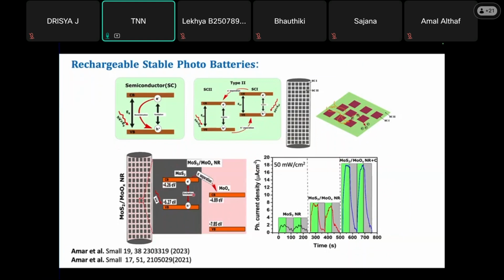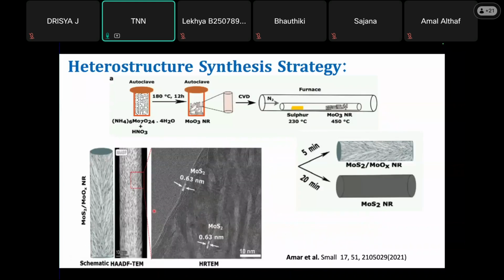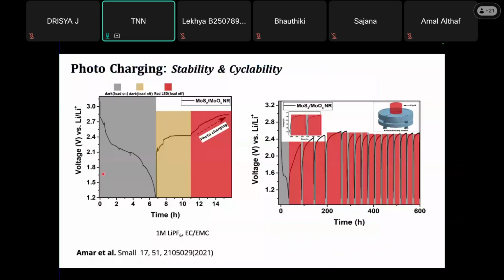Now, not only that, the holes generated should actually host the lithium. For example, in this particular MoS2 and MoOx, the MoS2 has to hold lithium ions, since it is a layered material like graphite, it can hold lithium. Holes should be generated at the MoS2, otherwise the holes cannot get accumulated here and the oxidation cannot happen. So all these conditions need to be satisfied while designing a material, and we found that in MoS2 to MoOx such a strategy can be obtained, and we created such a surface structure, type 2 semiconductor having both MoS2 and MoOx. I don't have time to explain all these things. If somebody is interested, I can go and detail it. But we showed that the photocharging happens for several hours and cycles.